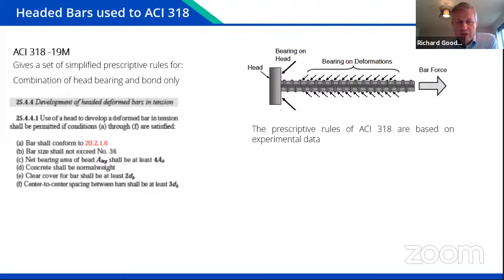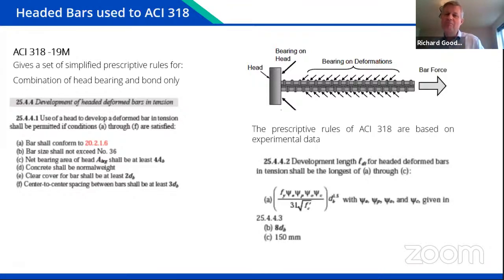And it says that normal weight concrete should be used, and then it gives the center to center and edge distance as multiples of the rebar diameter. And then the thing that changes is the bond or development length, which is a function of the concrete strength, the rebar diameter, the rebar strength, and a number of other factors, depending on whether it's epoxy coated or not, a location factor, a strength factor. So what changes then is not the spacing, but the rebar bond length requirement. But in fact, what is actually happening is, as you have a longer rebar bond length, there is less load on the head. Or if you have a shorter bond length, you get more load taken via head bearing.